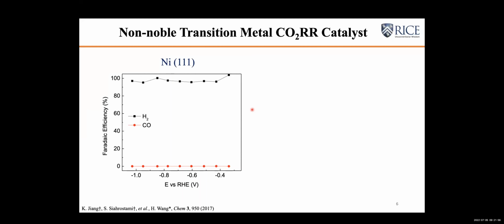And number two, the second reason is even more serious. For those transition metals, you can imagine if any CO2 gets reduced on the surface to produce CO, not only as a product, but also for some of the hydrocarbon generation, CO can serve as important intermediates. Those early transition metals, including nickel, cobalt, and iron, can bind CO very strongly.